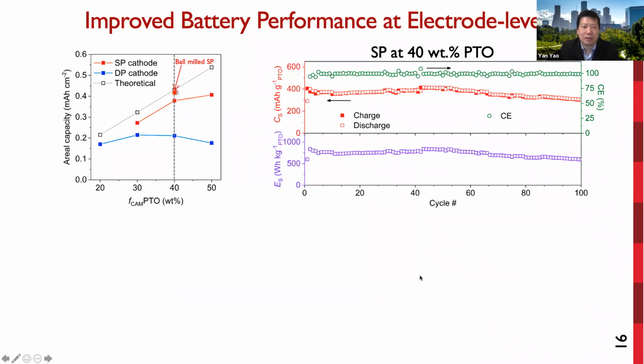So as a result, the areal capacity now scales with PTO mass fraction in this red line. In comparison, the dry process is the blue line. The material utilization can go up to 98%, and cycling stability is excellent over 100 cycles.